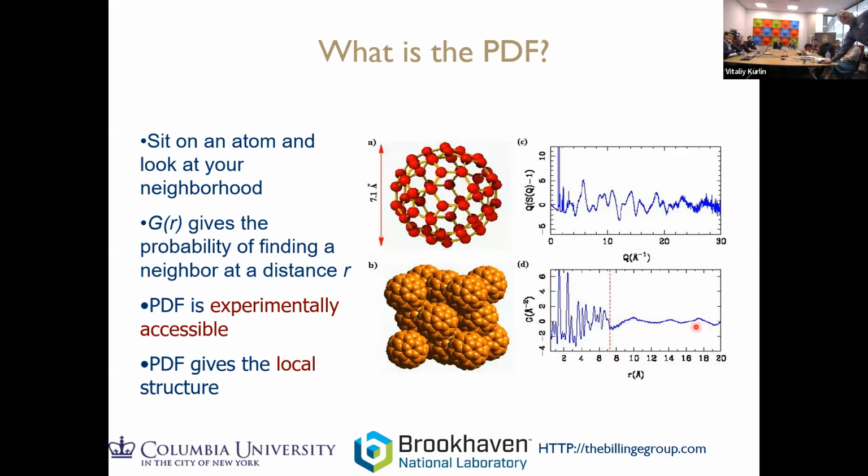And then what's happening out here? Well, what's happening out here is I have my molecules sort of ordered in space somehow. And I'm sitting on an atom on this guy, and I'm looking at an atom on that guy. And these things are spinning, they're dynamically reorienting at high speed because the data are collected at room temperature. So I can model that as a hollow sphere of uniform density, and I can make an FCC arrangement of these hollow spheres.